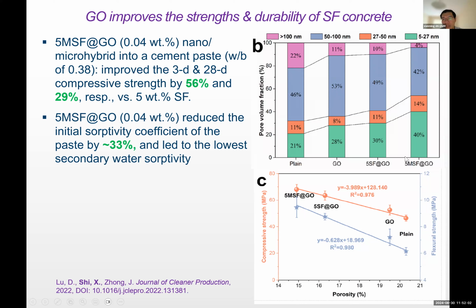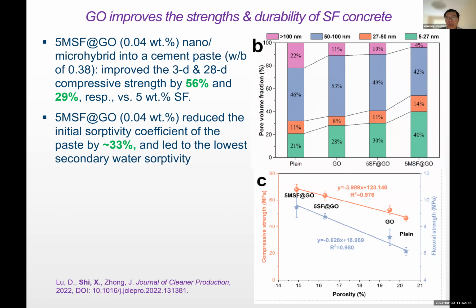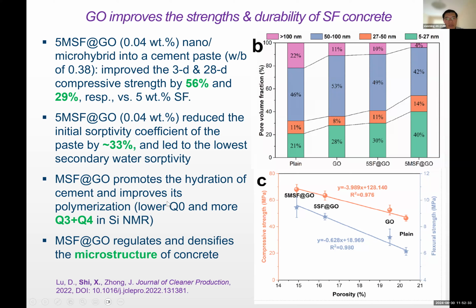The y-axis is the pore volume, and on the x-axis you can see the four different groups. Basically, the story is that with the pre-treatment of silica fume by graphene oxide, you increase the amount of finer pores, which are smaller than 100 nanometers, and reduce the amount of larger pores. So that's very desirable for better durability. And then again, we did NMR, which shows increased polymerization degree, and the chart at the bottom shows that if you move from the right towards the left, you are seeing increased compressive strength and also reduced porosity overall.